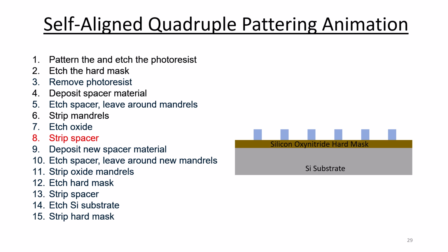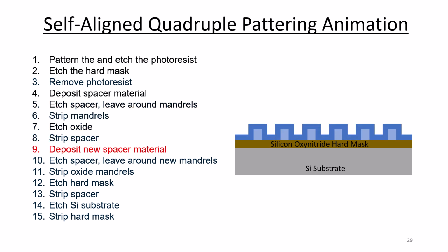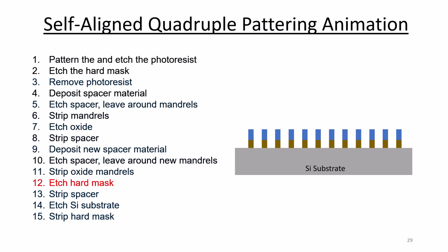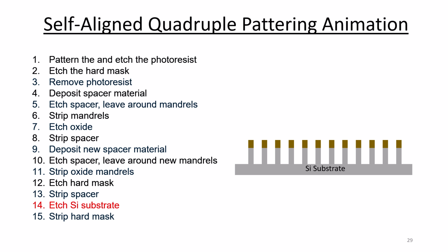We strip out the spacer material. We deposit new spacer material around the new oxide mandrels. We etch the spacer material. We strip away the oxide mandrels. We etch the hard mask. We remove the spacer material. Now we etch the silicon using the hard mask. Now we strip the hard mask. And what we end up with is 1/4 minimum pitch, and it's all self-aligned.